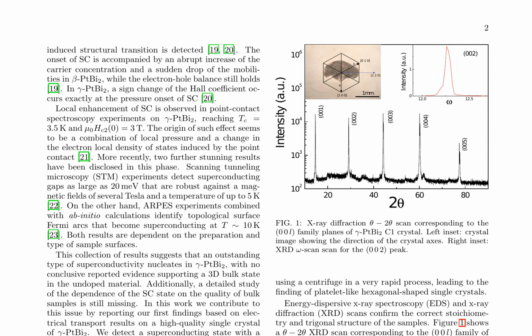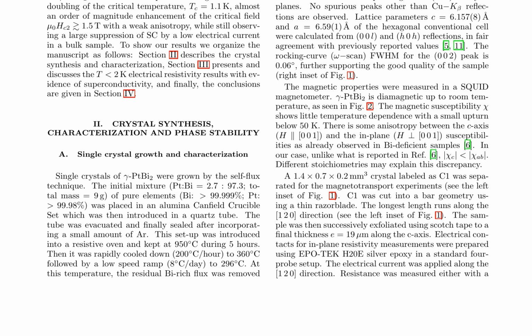Scanning tunneling microscopy experiments detect superconducting gaps as large as 20 meV, robust against magnetic fields and temperatures up to 5 K. ARPES experiments combined with ab initio calculations identify topological surface Fermi arcs that become superconducting at T approximately 10 K. The authors report their findings based on electrical transport results on a high-quality single crystal of gamma PtBi2, detecting a superconducting state with a doubling of the critical temperature, Tc equals 1.1 K, and almost an order of magnitude enhancement of the critical field, μ0Hc2 greater than 1.5 T, with weak anisotropy.